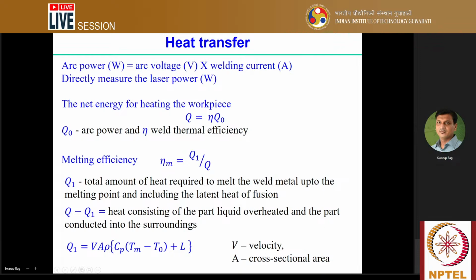But if you look at Q minus Q1, that amount of heat consists of the part that goes to liquid overheat, because in this case we are considering only up to the melting point. We are not considering the overheating or superheating of the liquid metal. So that part, along with the heat loss to the surroundings, accounts for Q minus Q1. So this is the overall energy balance in the laser or arc welding process.